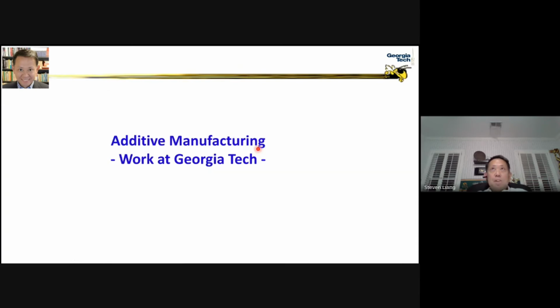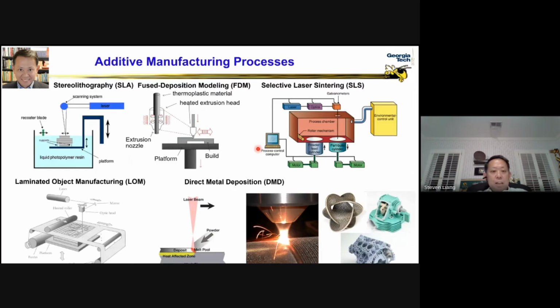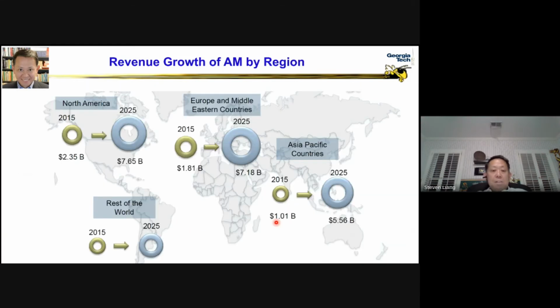Okay, so I don't have much time left, maybe a short 10-15 minutes to talk about additive manufacturing and what we have done at Georgia Tech. Of course, additive manufacturing is done on many different choices of material, like fluid material, paste material, powder, solid material, or film or paper or sheet material. And we have done quite a bit of work at Georgia Tech based upon the laser fusion of powder bed as well as powder feed configuration to generate different geometries. And this is an area, the additive manufacturing for metal. Now, we don't do much on polymer and ceramic and composite. We study exclusively metal.